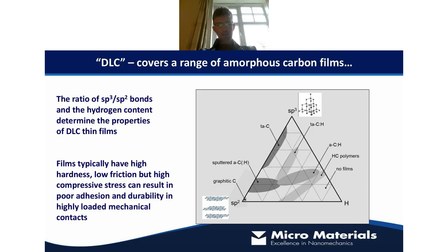So DLC, or diamond-like carbon, covers a wide range of amorphous carbon films where mechanical properties can be controlled by things like the sp3 to sp2 ratio and the hydrogen content. And when you add in doping as well, you can imagine you've got a very wide parameter space that coating designers can develop materials within.